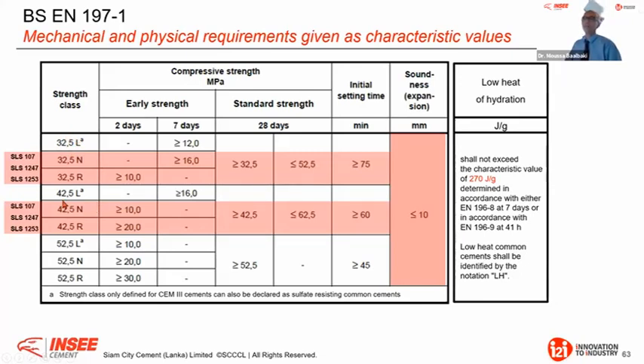And when it comes to the 42.5, the requirement is exactly like the 32.5, 16 MPa, okay? Now, more requirements for the 52.5. We do not have the 52.5 in Sri Lanka, even though if I take the 42.5 R, that is 20 MPa, it can be equivalent to the 52.5, and at the same time the 42.5 R is between 42.5 and 52.5. If you look at our product, we are around 55 MPa, and you are also a 42.5 N.